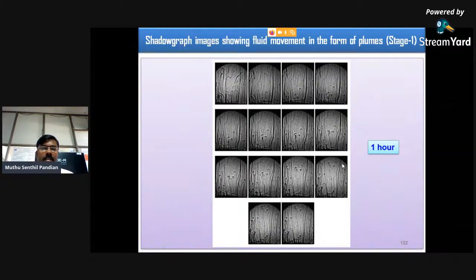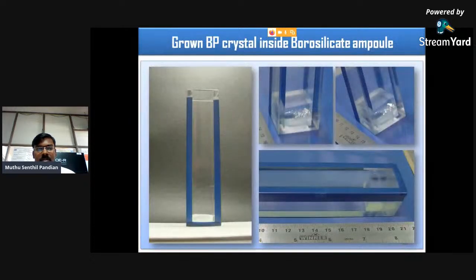So from this shadowgraphy and Mach-Zehnder interferometry, we can easily conclude that gravity-driven concentration is solely responsible for the growth of the SR method grown crystal. For this purpose, we have selected this benzoin crystal. This is the quartz sample we have selected for the interferometry and shadowgraphy images. And this is the as-grown benzoin single crystal.